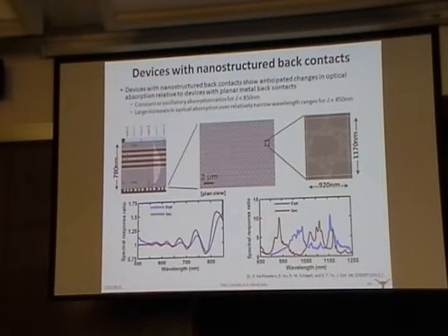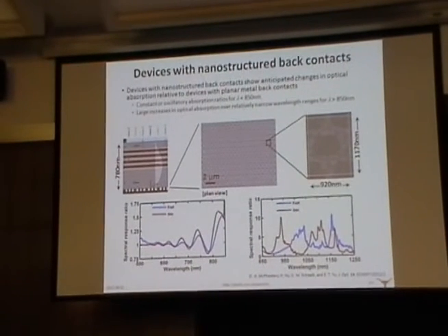They don't exactly overlap because the wavelengths at which these occur are very sensitive to the exact dimensions, and what we fabricate is not exactly the same as what's designed or simulated. But you see generically the same sorts of features and roughly the same magnitude of increase in the absorption. So it seems like experimentally these ideas work. And then the question is, what is the best that you can do, or how well can you do with these kinds of approaches in getting high absolute absorption efficiency, particularly if you're constrained to have thin multiple quantum well stacks that are required to efficiently extract the carriers.